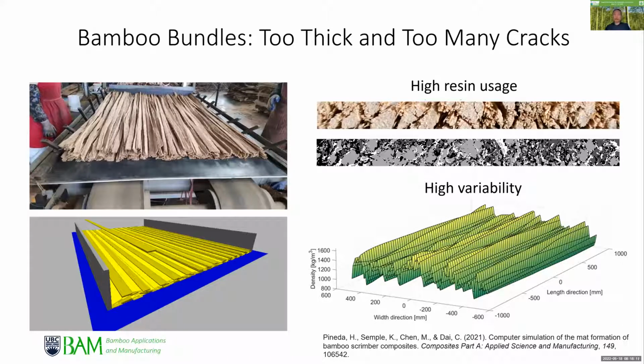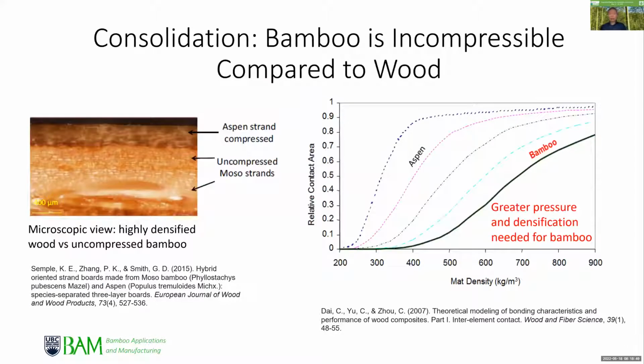If we look at how the bamboo scrimber is formed, and at the thickness of the scrimber itself, the piece of bamboo is just too thick, and it causes a lot of variation. Also, in preparing the bamboo strips, there are a lot of internal cracks that take place and need to be filled with resins. That was the main reason that the resin content has to be so high. So this is one of the processing areas where we think there's potential to improve.